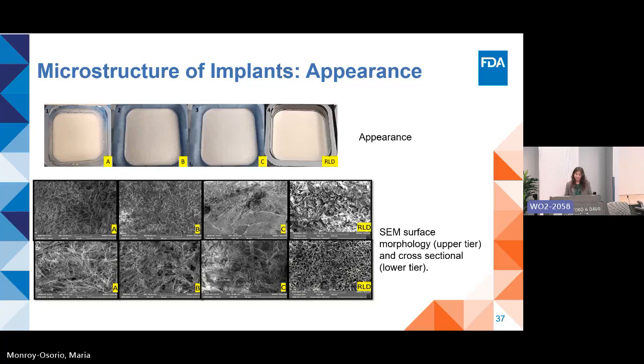So here, the first thing was to characterize the implant formation once we manufacture the implant. As you can see in this slide, implants A, B, C, manufactured by using collagen from source A, B, C, are formed completely and compared with the RLD. However, implant A shows a rough surface with noticeable adhesion of the collagen to the containers compared to B, C, and RLD, which have a smooth surface and some extent of adhesion to the container.